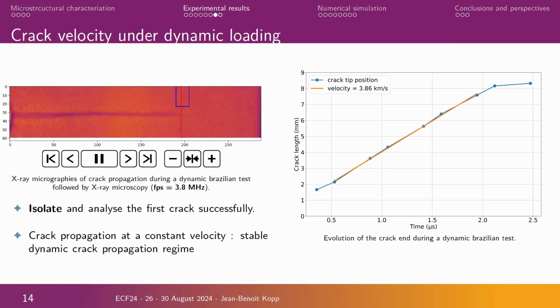And with this test, as we have isolated just a main crack in dynamic regime, it is possible by using a dynamic fracture approach to estimate the dynamic fracture energy. So that we have done. So we isolate one crack, which was followed to estimate the crack path history. So the crack length as a function of time. During the propagation, we can observe that we have a quasi-constant crack velocity. That means that we have a stable dynamic propagation regime. And if we have that, it is possible to estimate rigorously the dynamic fracture energy.